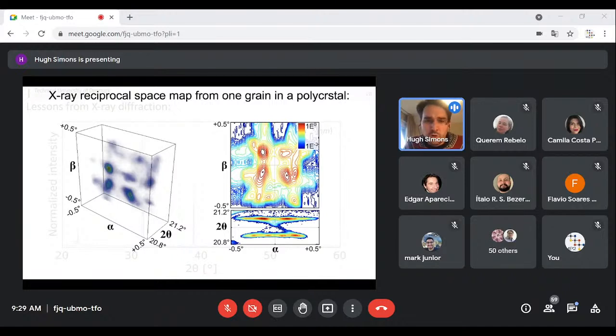But the problem is that you lose all of this information when you average it together in a powder diffraction pattern. And all of these, essentially this misplaced intensity, I would say, this diffuse intensity, corresponds to symmetry breaking. And this is a really big issue because, as I said, our understanding of these materials is based on the underlying assumption that they have a given symmetry, like tetragonal in this example. And if the material is strained, then it breaks that symmetry. So then you have to start questioning your underlying assumptions about why the materials behave the way that they do.